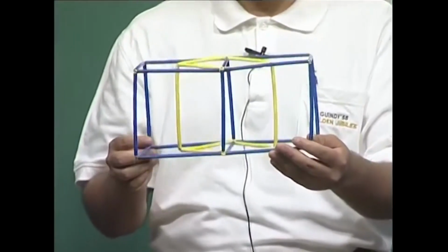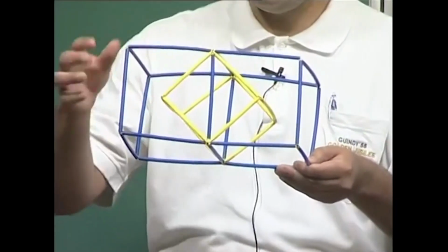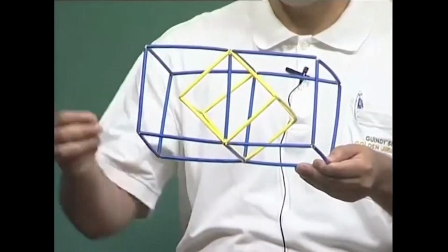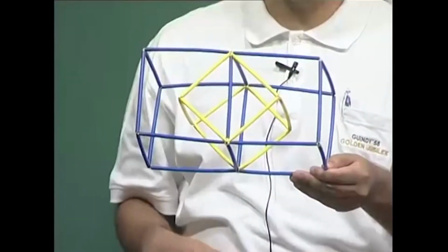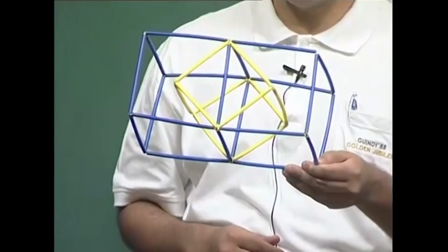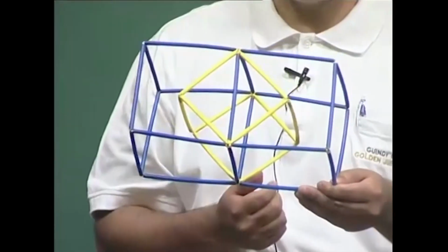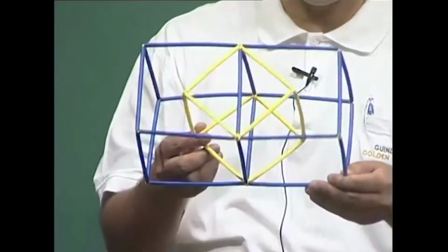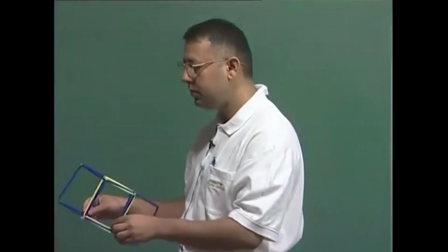So, looking at the figure once more, you can see from this angle also that I have this blue unit cell, which is two unit cells of the cubic lattice. I introduce a lattice point at the top and the bottom to forcefully make something known as a C-centered cubic, which we consider to be banned because of the violation of symmetry of the cubic lattices, but then we can go ahead and make an alternate unit cell, which is the yellow unit cell, which is nothing but a simple tetragonal cell.